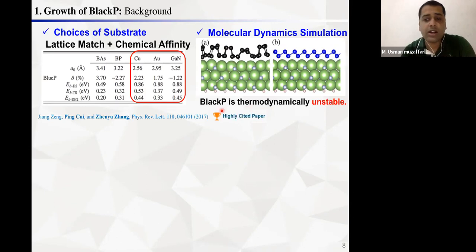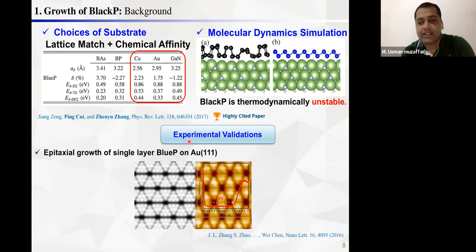So eventually we ended this project as a byproduct, and we published this paper. Luckily, we published it in PRL. In the same year, we found an experimental report of blue phosphorene grown on gold, which is one of the predicted substrates in our paper. This paper appeared in Nano Letters in 2016. This shows the predictive power of density functional theory, so we use this as a reliable tool for predicting materials, especially in the growth field.